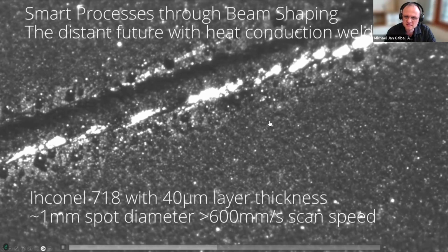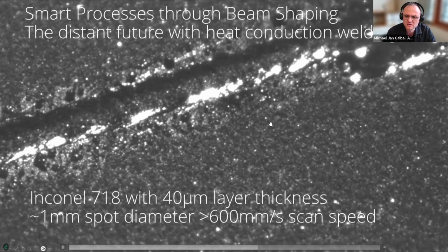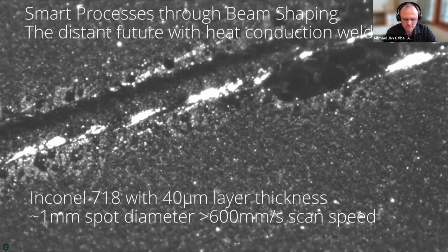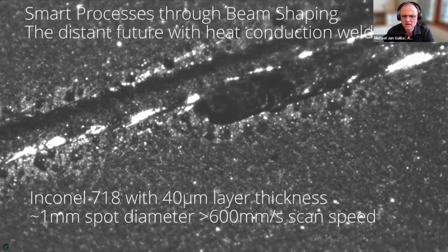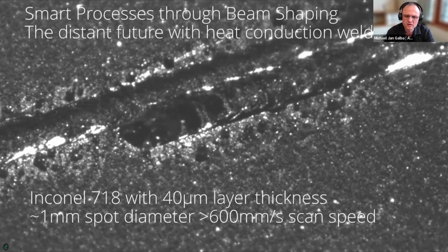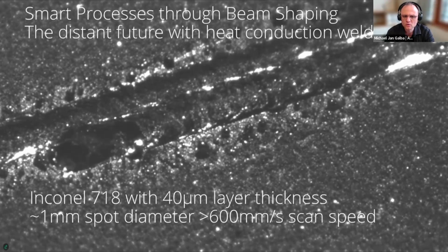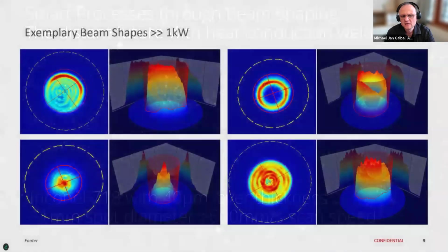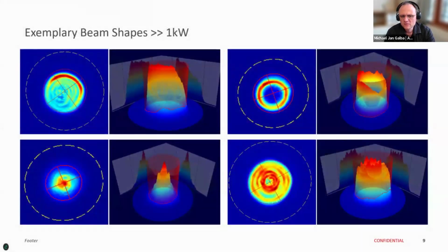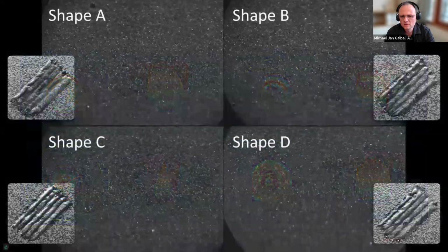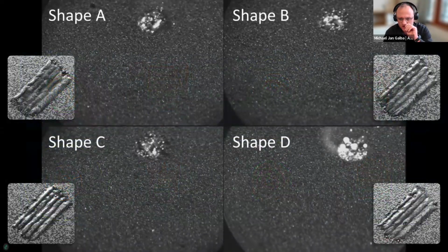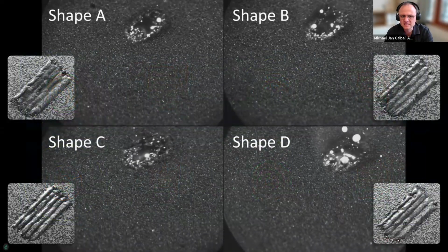Charmingly as well, this heat conduction welding process does not emit any side products. So what you see here is just a very, very clean melting of the material and not a laser welding where you have these spatters flying all around, causing disturbances in the process. Here we've tried different beam shapes and how they interact with the powder, and all again showing a very different melting behavior.